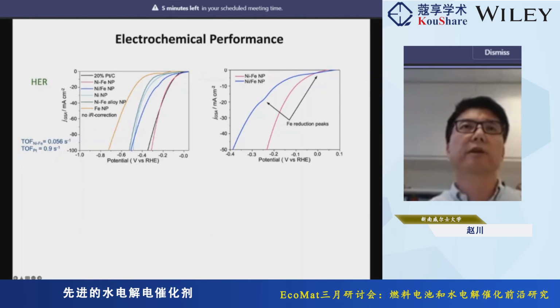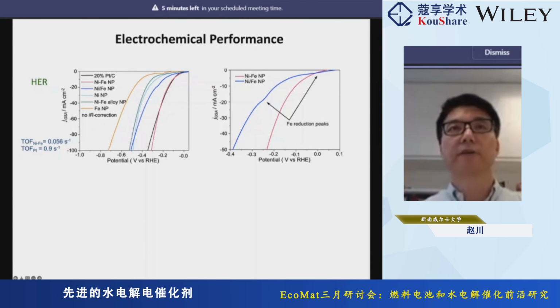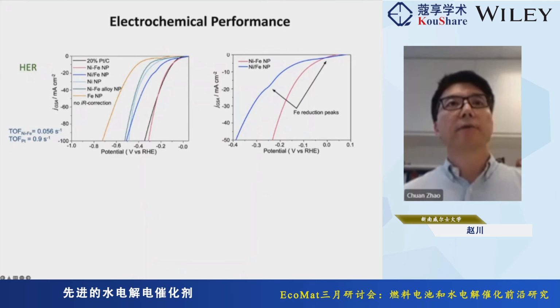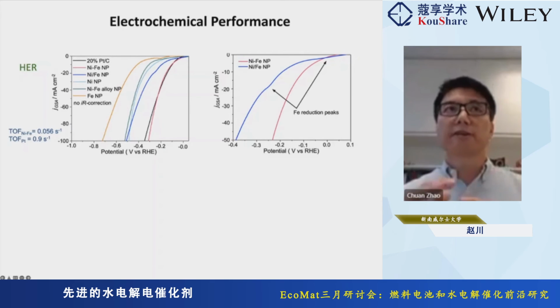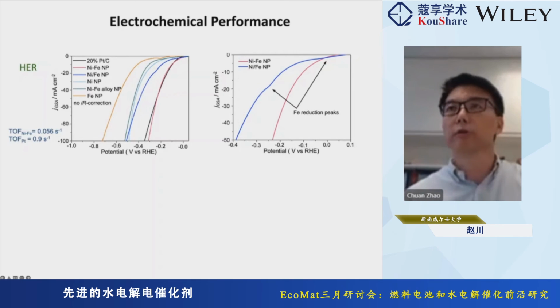What we have here almost approaches platinum for HER. For comparison, we also prepared a nickel iron nanoparticle with a physical mixing of the both. What we can see here is the activity is much lower. We also made the nickel iron alloy, and also found the activity is much lower. This suggests the nickel and iron oxide interface is very unique for the HER performance.